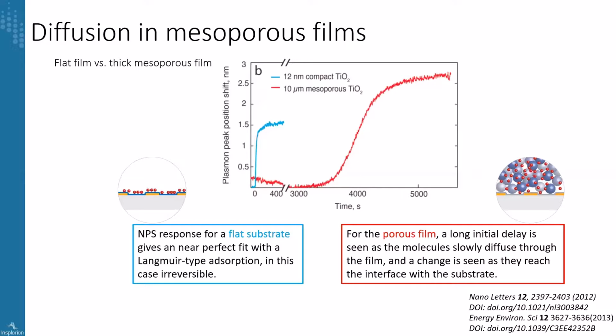In comparison, you have the red graph, which corresponds to 10 micrometer mesoporous titanium film. And I'd like to remind you that we're only sensitive on the first 30 nanometers closer to the surface. So of course, if you have a much thicker film, even if it's porous, it will take a longer time for the dye to reach the surface. So of course, the response time is closer to the hour mark rather than just a few seconds. So this is a great example to show how you can use the fact that we're very surface sensitive to your advantage.